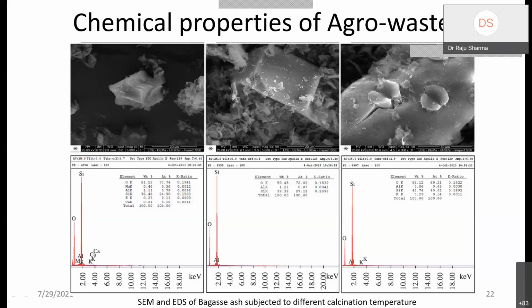So when you move from 500 to the next temperature, right? The next temperature was 600. When you move towards 600, you can see the silica content in the embedded table of the central bottom EDS image, where SiK has a weight percentage of 39 and atomic percentage of 27. If you compare with the previous one, the silica is getting higher. If you go to a higher temperature, silica is 42% and atomic percent is 30%. So it is increasing the amount of silica in the paste.